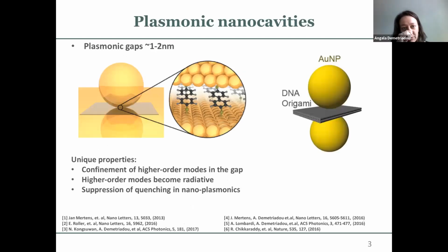Okay, so when I refer to plasmonic nanoantennas and plasmonic nanocavities, all the systems that I'm dealing with, I'm talking about plasmonic gaps that are only 1 or 2 nanometers in width, or height, sorry, the height of the plasmonic nanogap. These are extreme cavities, very, very small gaps, and recently in 2014, 15, I think, they were first fabricated, and the way that experimentalists fabricate them, mostly, is what I'm showing here on the left.